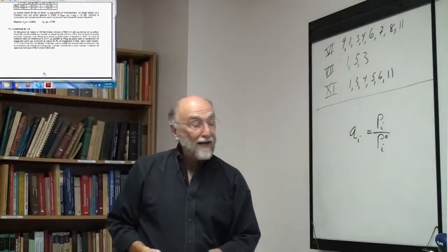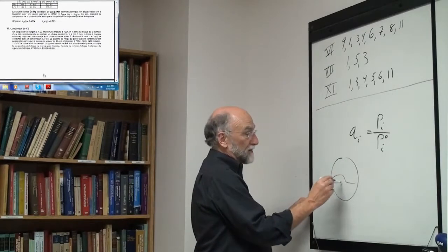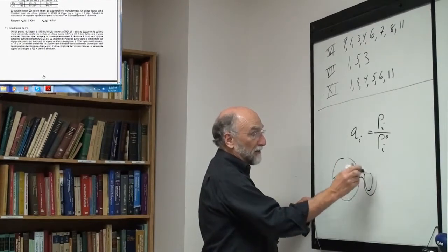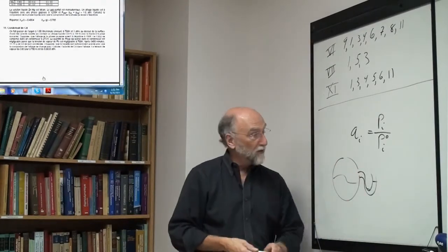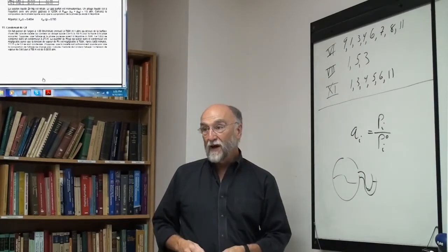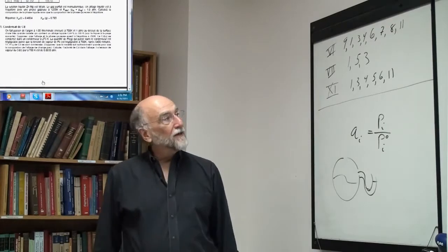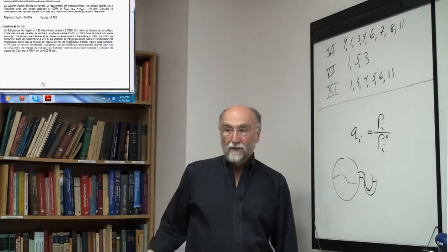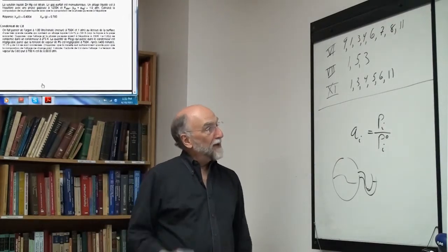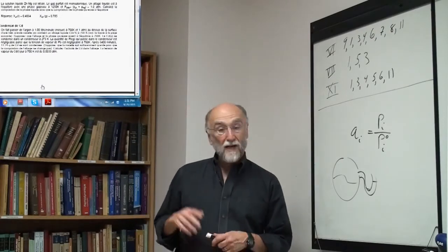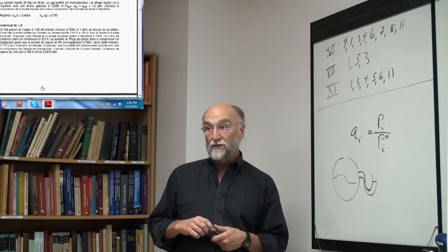You can measure it directly. If you have your material here, and here you have a pressure gauge, a little manometer, you can measure the pressure, but obviously only if the pressure is reasonably high. Okay. You can use a mass spectrometer. We'll talk about mass spectrometers later, but the mass spectrometer is only good for very low partial pressures.